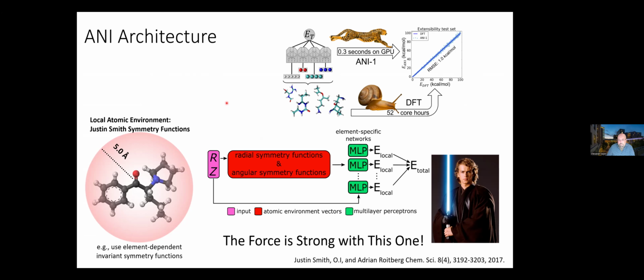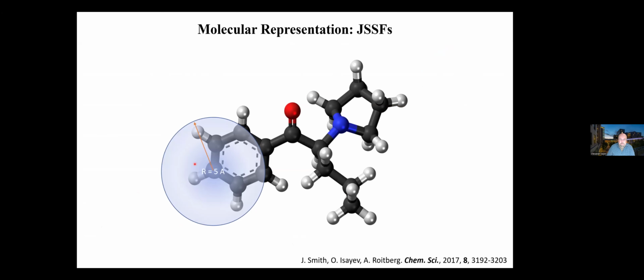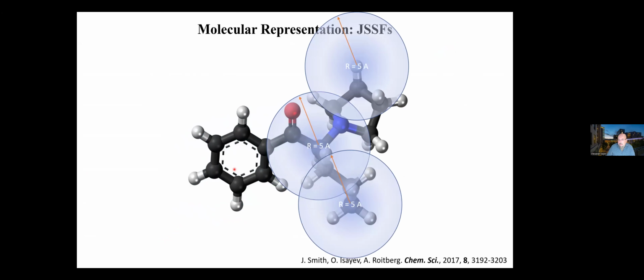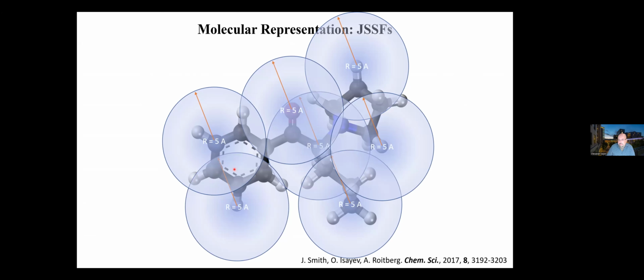The idea of the neural network: you take your molecular structure, and every atom inside the molecule or a material would be characterized by the spherical environment, which we call the symmetry function, up to a certain cutoff radius. This spherical environment encodes the atomic neighborhood, essentially all your neighbors until the cutoff. And what is essentially happening, your neural network zooms in on one environment at a time, and the total energy of the system would be the sum of these atomic environments.